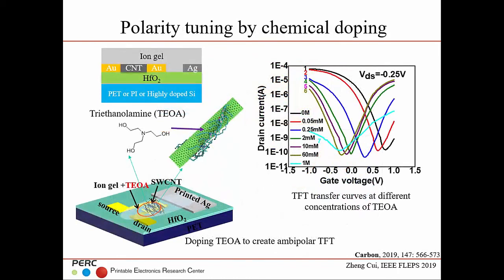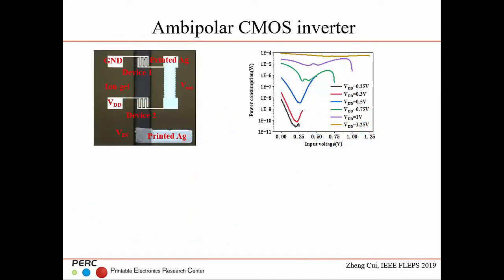And the third way we make the P-type into N-type carbon nanotube, we use what we call chemical doping. This particular TEOA material, when we deposit it onto the carbon nanotube, changes the polarity of the carbon nanotube into what is called ambipolar. So when I apply a different voltage, the carbon nanotube appears to be ambipolar. So for the ambipolar transistor, we also make the inverter. That's the same carbon nanotube, but with chemical doping, we can make the ambipolar one connected with inkjet printed electrode. So that's showing that at the off state the power consumption is also very low.